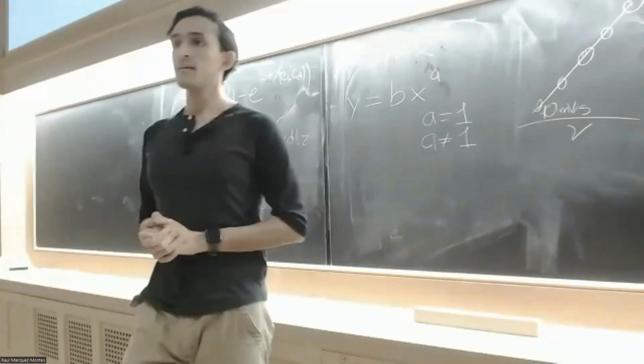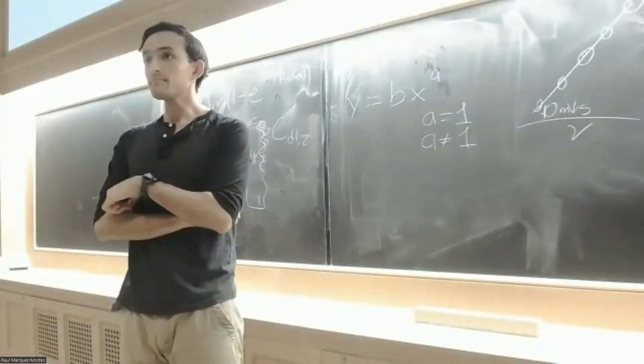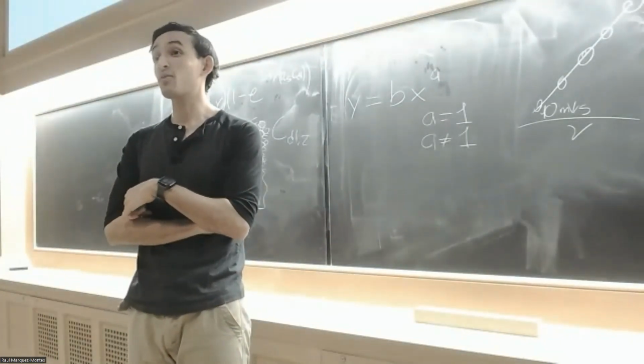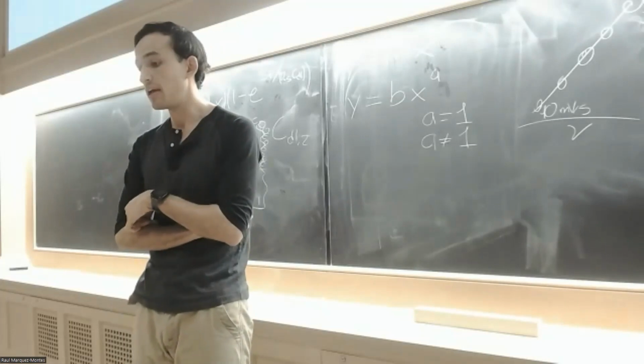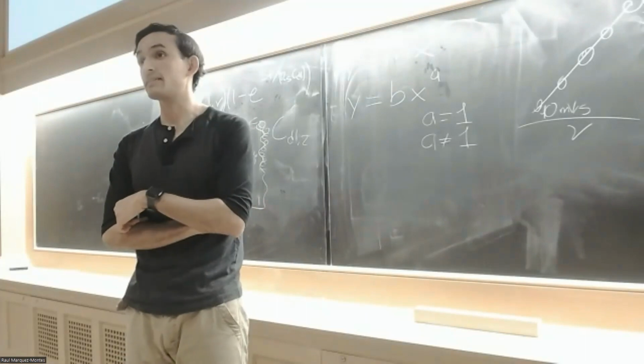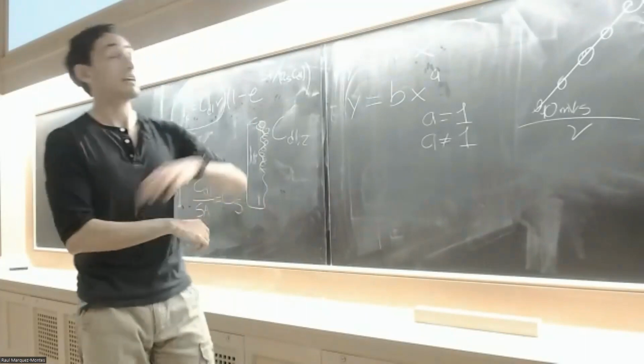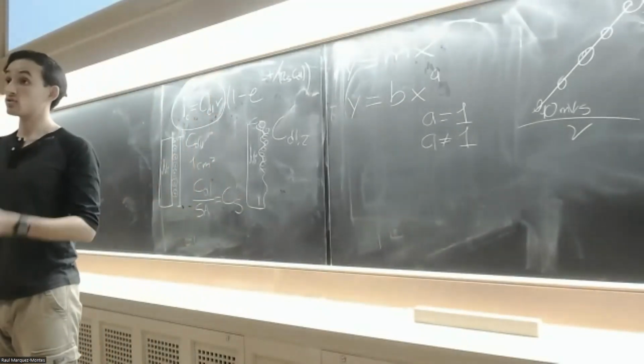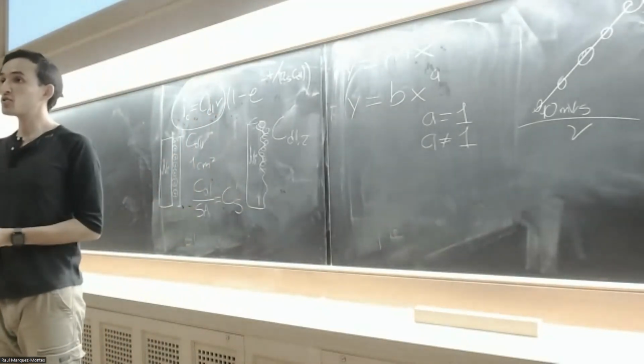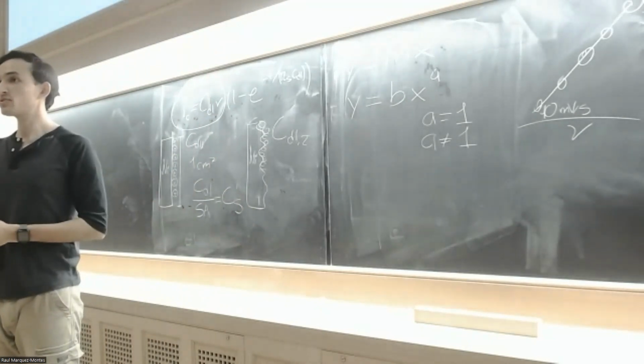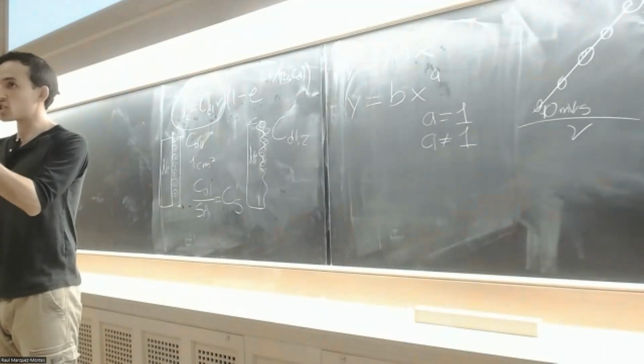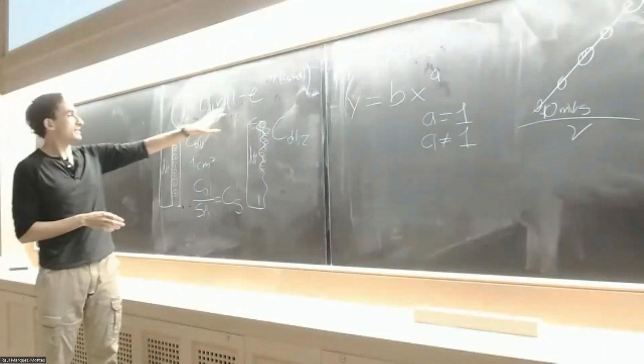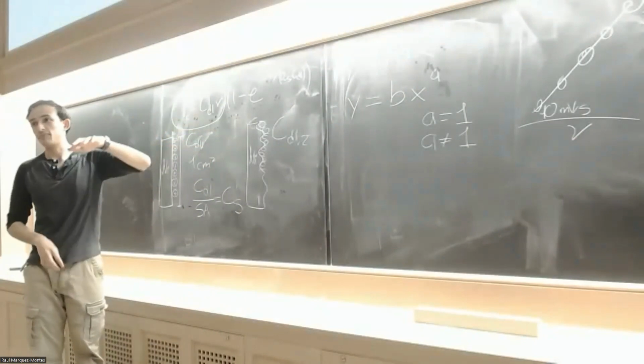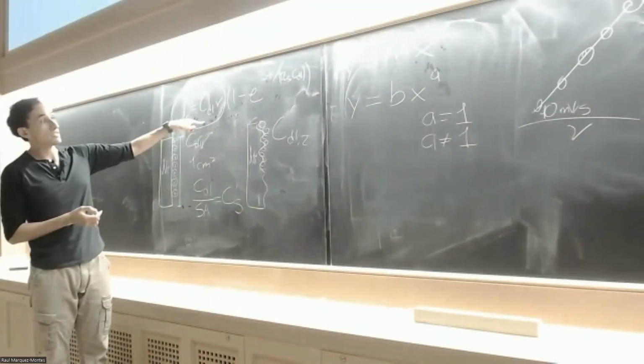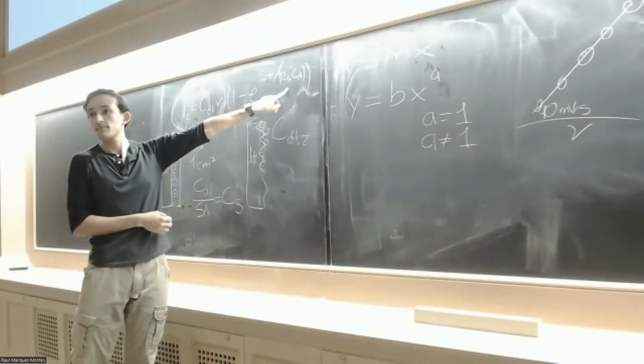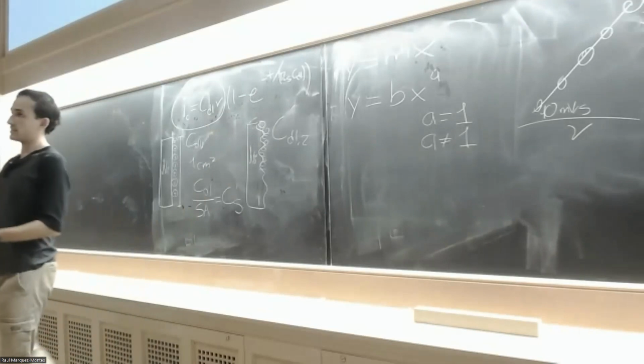If you use different organic solvents, will your capacitance change? That's a great question. The thing about organic solvents is that they may have different conductivities. So the double layer capacitance depends a lot on the solvent that you use as well, right? So you should be careful with what kind of solvents you use, not because the double layer capacitance may change. Like in the equation here, notice that instead of the double layer capacitance changing because of the solvent, the term that is going to affect the most is the resistance. So the resistance is the main reason why you should stick to one solvent.